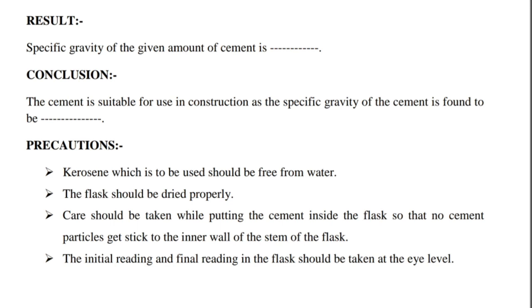Precautions: The kerosene used should be free from water. The flask should be dried properly. Care should be taken while putting the cement inside the flask so that no cement particles stick to the inner wall of the stem. The initial reading and final reading in the flask should be taken at eye level.